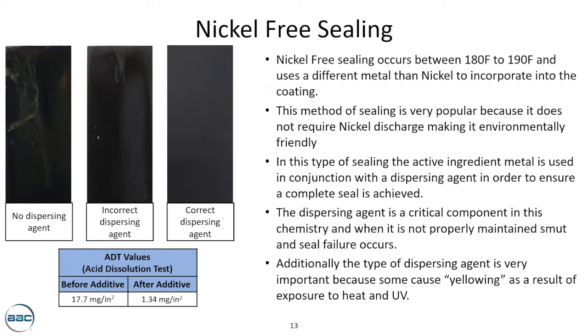So based off of this data, as a rule, nickel sealing, because it uses nickel, will give you an improvement because it does filter UV light. So keep that in mind whenever you're selecting your seals. There is a benefit of nickel as it relates to operating margin and being able to have a poor seal, but by having nickel in the coating, regardless of whether it's a good or bad seal, you're going to get some benefit.